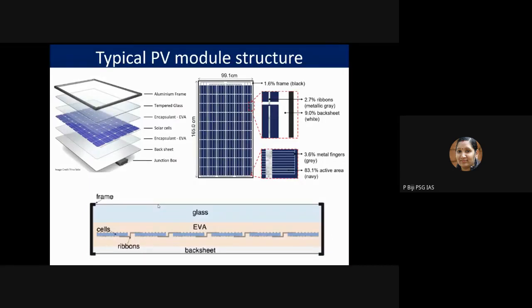We call it EVA. EVA is nothing but ethylene vinyl acetate. It's a polymer. The electrically connected cells are sandwiched between two EVA sheets. You can see from this figure, it's called encapsulant EVA. So the solar cell is sandwiched between two EVA sheets, and on the other side, the front side, you have your tempered glass. That's the solar cover glass, and on the back side you have a multi-layer back sheet. During this lamination process, the encapsulation happens, and this EVA acts as a glue which encapsulates this solar cell as an electrically isolated as well as environmentally protected structure. That's basically the lamination, and after that it will be cured. So that's the basic PV module manufacturing process.